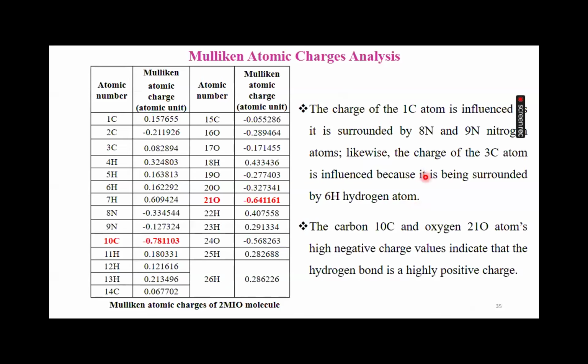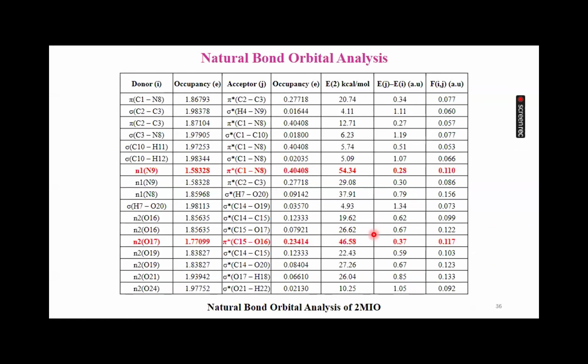Mulliken atomic charge analysis. The negative and positive charge values of the carbon and oxygens, high negative charge values are indicated, with hydrogen having highly positive values. Natural bond orbital analysis. The natural bond orbital analysis was undertaken for all bonding orbital interactions occurring between filled Lewis-type orbitals, called donors, and empty non-Lewis-type orbitals, called acceptors, such that the stabilization energies E2 were determined by second order perturbation theory.